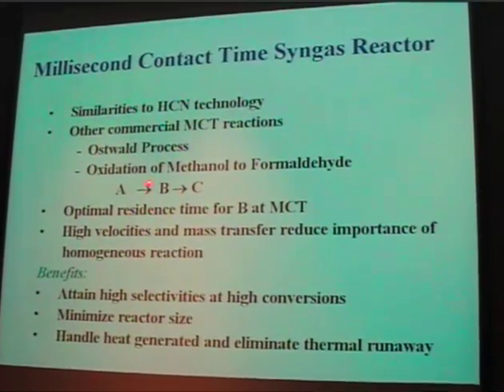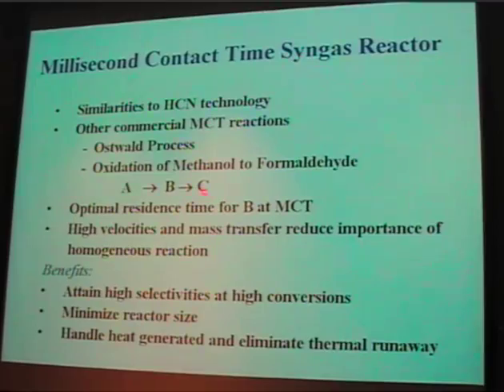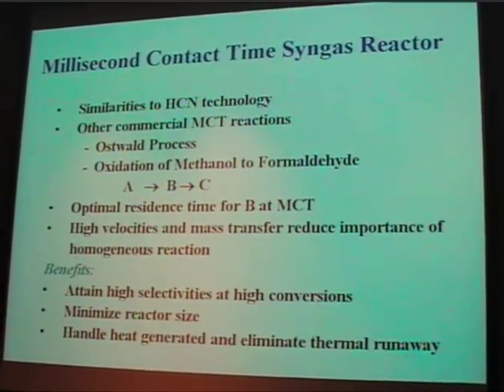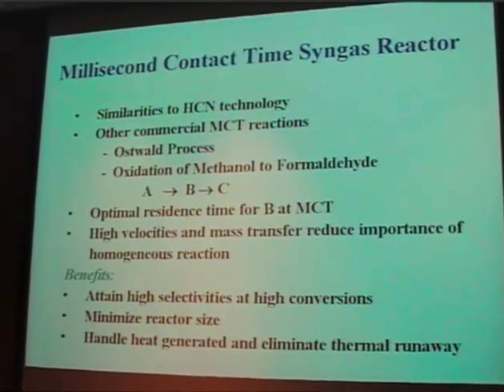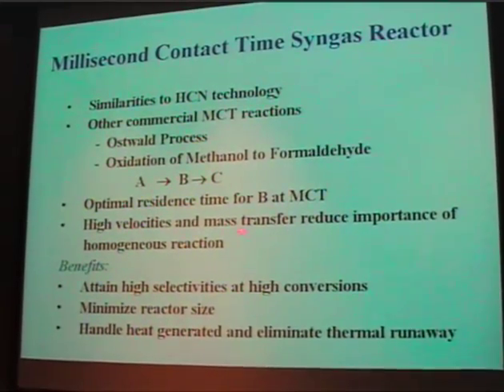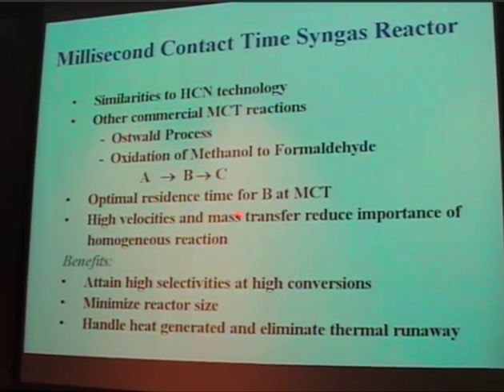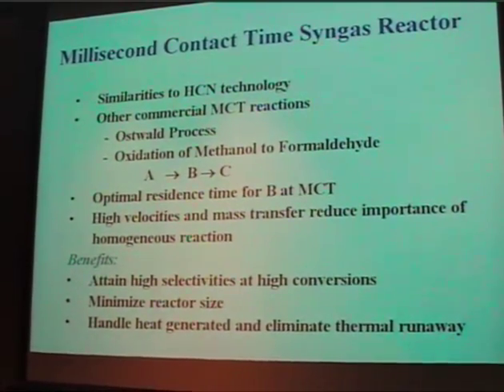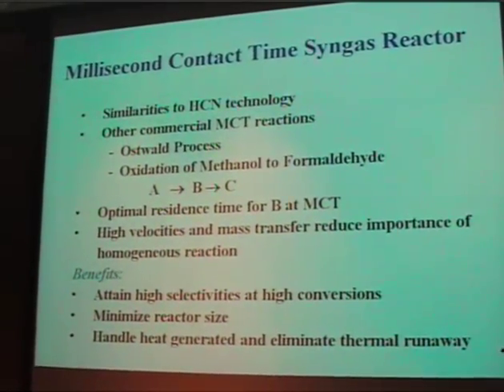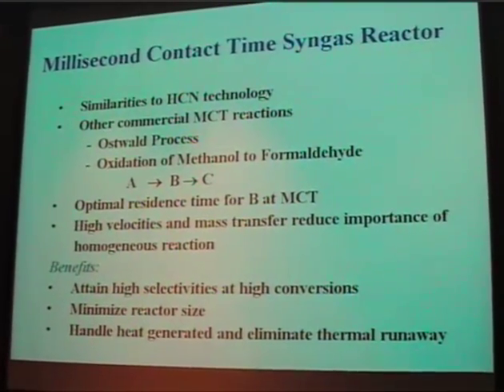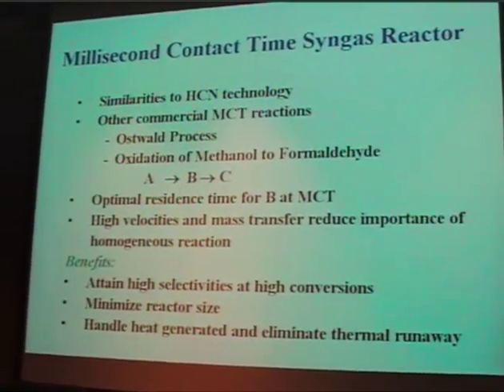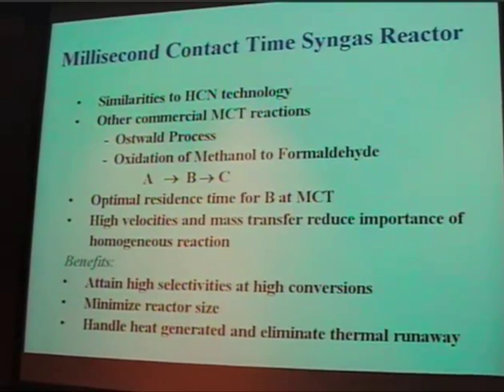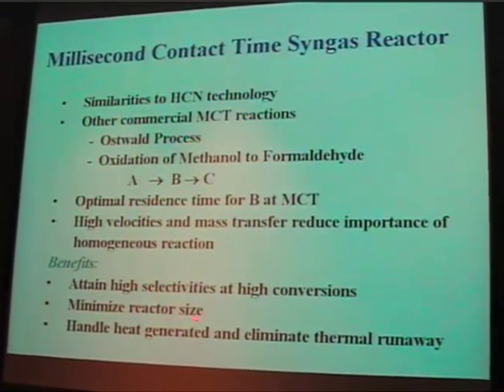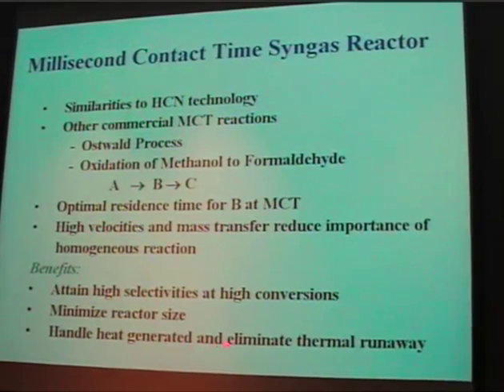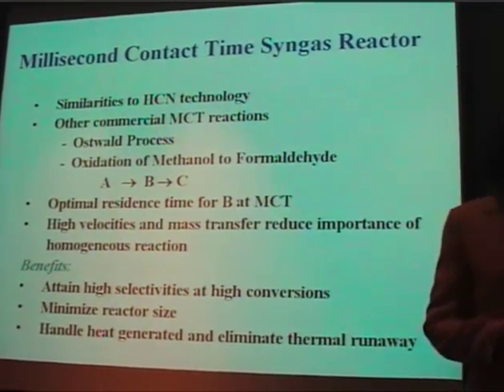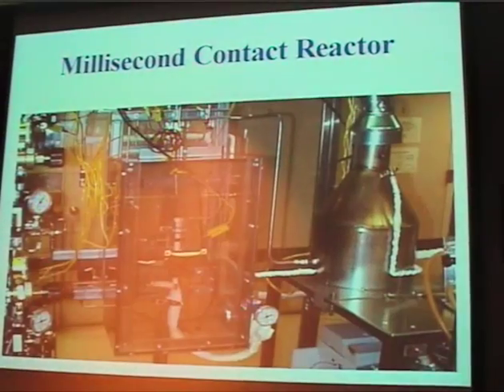So there's certainly a track record out there for thinking of a millisecond contact time. Basically, you want to make it favorable to go from A to B and not continue on to C by optimizing the residence time. And doing that with high velocities, you can get the mass transfer that you need, and then minimize unattractive homogeneous reactions. So the benefits are you can achieve high conversions and high selectivities at a high throughput rate, therefore you can minimize your reactor size and yet be able to handle the heat and prevent thermal runaway.